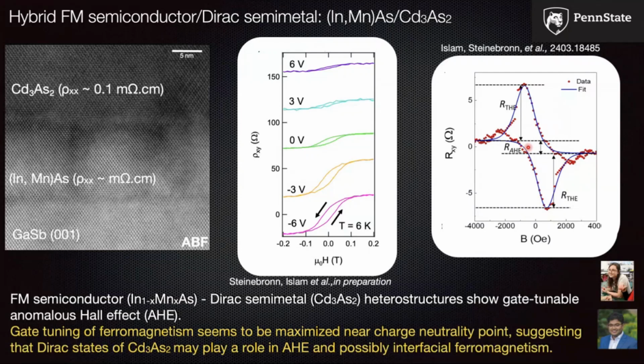Now, why is this interesting for metrology? Well, it turns out that we can grow cadmium arsenide in a particular orientation and geometry where, if the cadmium arsenide is thin enough, then it becomes a topological insulator rather than a topological semi-metal. And in that case, unlike the chromium-doped bismuth antimony telluride, you now have a high mobility material in which you have these Dirac states, and you can proximitize magnetism perhaps by growing on an appropriate ferromagnet. So this is something that I'm very interested in discussing and pursuing. We are trying to do it ourselves, but we would love to collaborate with other people also in this context.